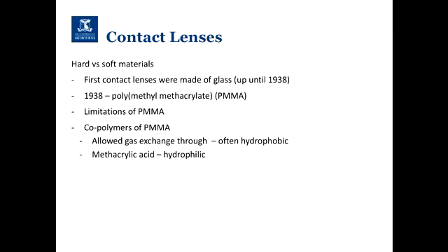So then they often will add methacrylic acid as the hydrophilic component to then counterbalance. You have something that is hydrophobic that allows gas exchange, but then you have another part of the copolymer which is more hydrophilic, so that it will still interact with the water.